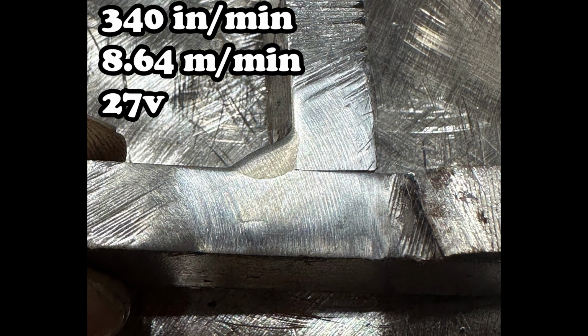Two things right off the bat. One, my travel speed was a little bit fast. I deposited a little bit small of a weld given the settings. And two, I hit the bottom plate more than the upright plate. Partially too, the molten puddle probably sagged a little bit. But realistically, had I hit more of the upright plate for a 45-degree angle, it still wouldn't have fused the root any better, I guarantee you that.